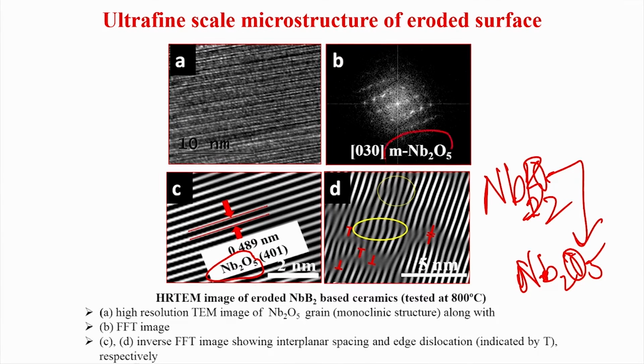And you see that Nb2O5 is a monoclinic phase, and this Nb2O5 also has a lattice spacing of 0.489 nanometer. And if you look at the right hand images, you see there is a bunch of edge dislocations, and these edge dislocations are positive and negative edge dislocations. At some of the places positive and negative edge dislocations have come together, and then they can annihilate, and they can form a very clear lattice plane.